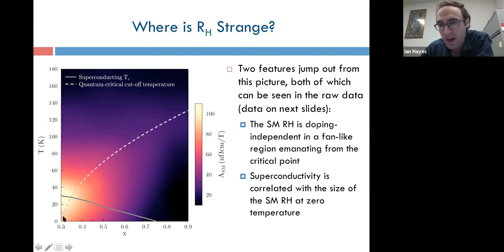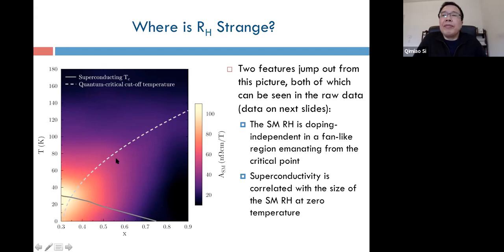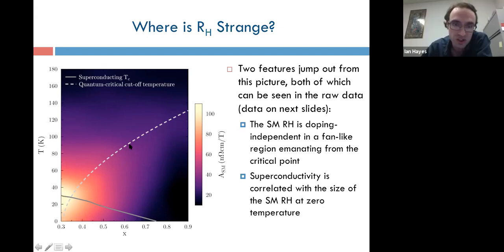The other thing I'll point out is that the antiferromagnetic phase actually ends at 28%. So I'm a bit off the exact critical points, you might say. That was chosen to just make sure we avoid accidentally entering the antiferromagnetic phase. Fair enough. Your observation is fair, and this is really just a guide to the eye determined by the data points that I have, and there's only so much I can say down here. But it may well be consistent with a small cutoff.